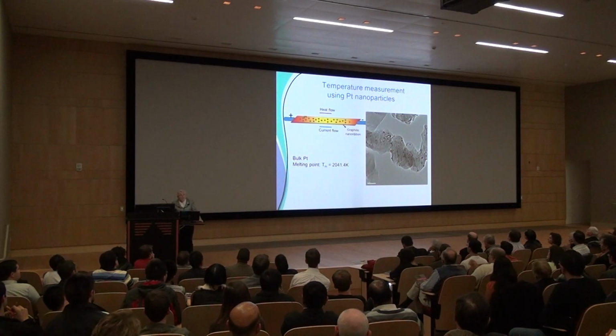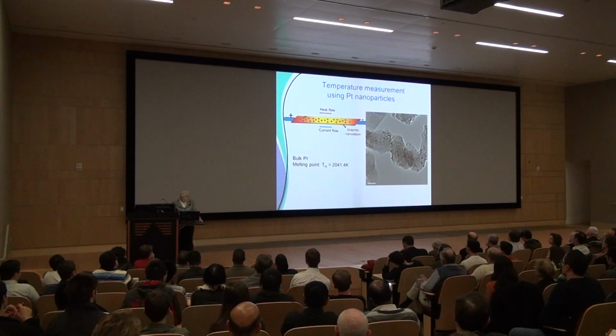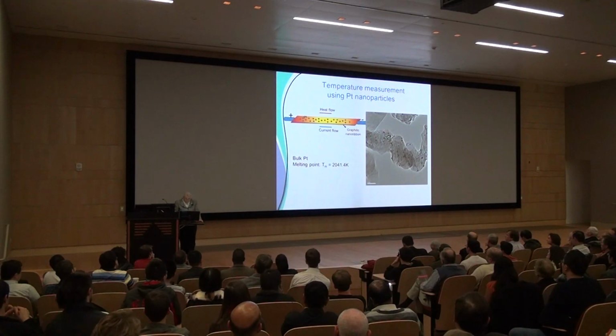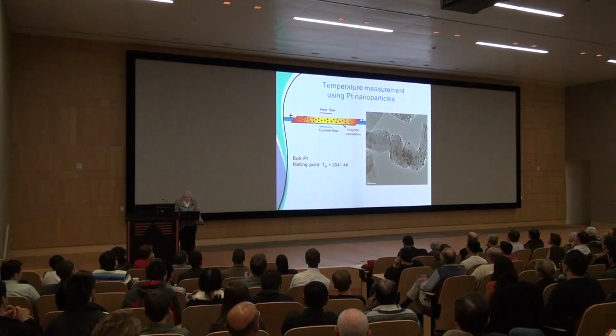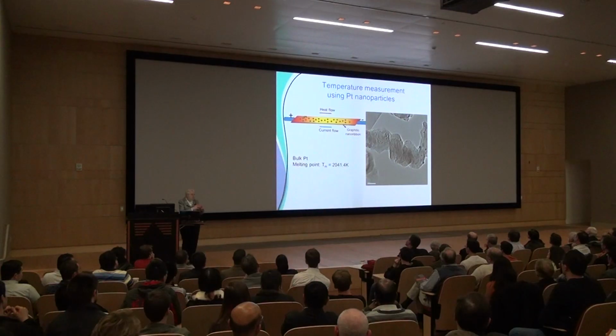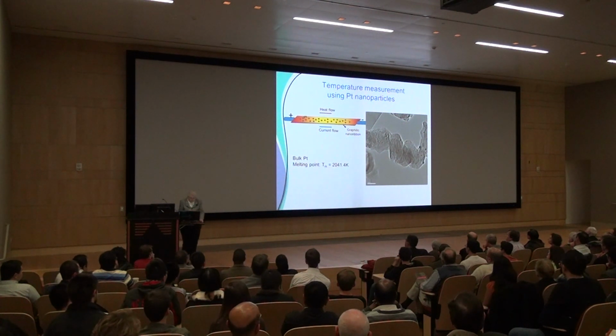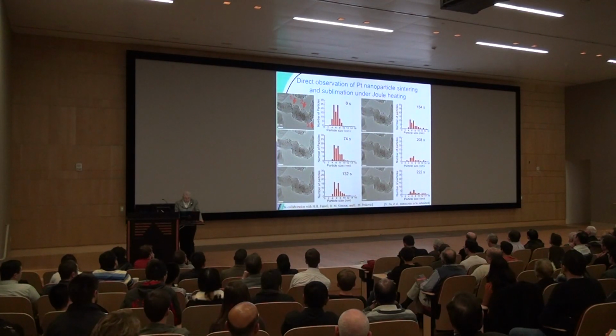And it also raises the point that we need to do some metrology to get good sensors for temperature measurement at 2,000 degrees. We don't really have them. And you can see here what happens. You get accretion, so that some of the little particles get bigger and others evaporate. And you have to do the balance of those two processes to figure out what the temperature is. That's what we're doing with this, but it's not very good or very accurate.